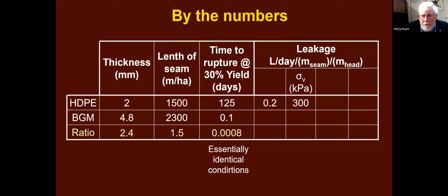This wasn't done for comparative purposes, but if we look at the HDPE, we're dealing with much higher stresses. We applied 300 kilopascals, and our leakage in terms of litres per day per metre of seam that's failed or was never proper in the first place, per metre of head. So we take the leakage, we divide it by the number of days to get a rate, we divide it by the length of the defect, and we divide it by the head. And that gives us 0.2.